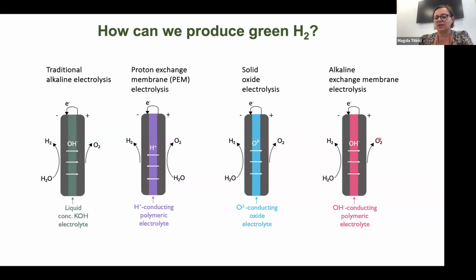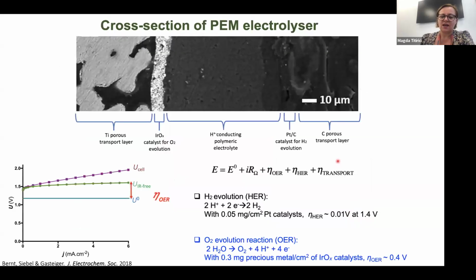And the nice thing about this technology is that you don't need to use critical metals for the oxygen evolution reaction at the anode, but then the kinetics on hydrogen evolution here are a bit slower. Nevertheless, if we take, for example, a PEM electrolyzer and go through a cross-section of this, you would see that the anode is composed of an iridium oxide layer that is quite thick, which is deposited on a porous titanium. This is the conductive Nafion in the middle, and then you have a little platinum deposited on